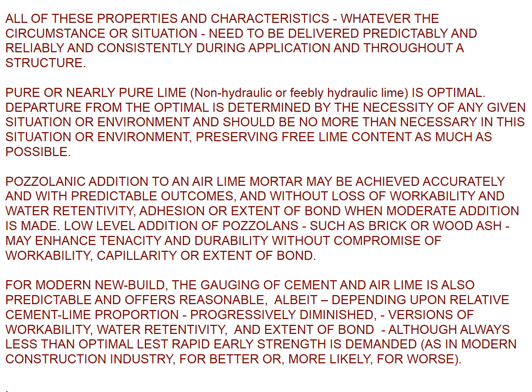Low-level addition of pozzolan such as brick or wood ash may enhance tenacity and durability without compromise of workability, capillarity, or extent of bond. For modern new build, the gauging of cement and air lime is also predictable and offers reasonable, albeit, depending upon relative cement lime proportion, progressively diminished versions of workability, water retentivity, and extent of bond. Although always less than optimal, lest rapid early strength is demanded, as in the modern construction industry, for better or more likely for worse.